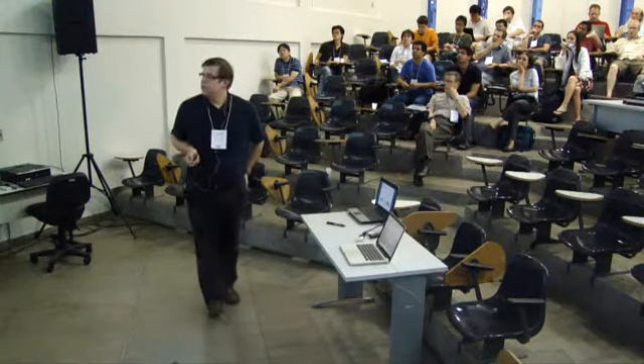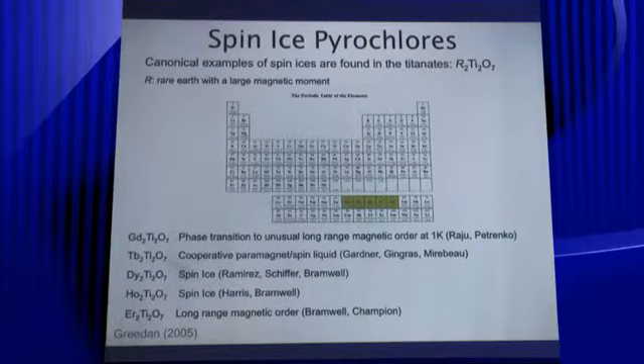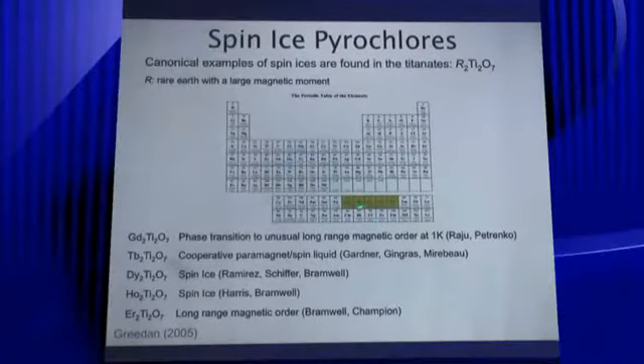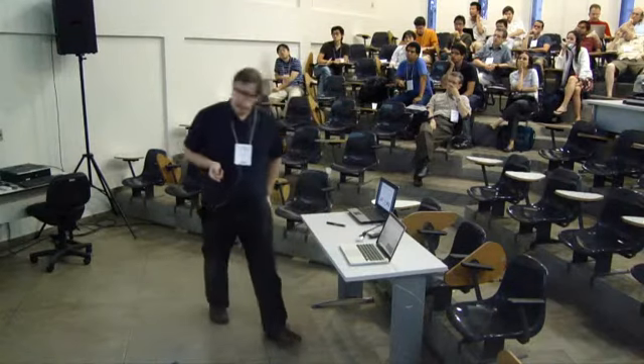So just as a quick review, there are only two known members here that are good examples of spin ice. It's not to say there's no interesting physics in these other compounds. As you go across these series, I mentioned this week that terbium titanate is a cooperative paramagnet. Gadolinium titanate has this unusual phase transition around 1 Kelvin. People are still trying to understand. And erbium titanate has this long-range magnetic state with the XY spins, but it's ordered by a disorder mechanism. So there's still interesting physics to probe as you go across here, but the only known spin ices among titanates are dysprosium and holmium.